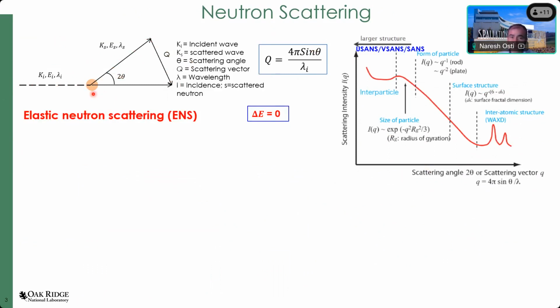If the scattering event is totally elastic, that means there is no energy exchange between the neutron and the scattering domain. At that time, if you plot the scattering intensity as a function of the momentum transfer vector, you end up with a scattering pattern that looks like this. The intensity decay profile at the intermediate Q regime becomes the signature of the size or the shape of the particles. Depending upon whether you have a spherical particle or an elongated particle, you may end up with a different slope of this intensity decay profile.